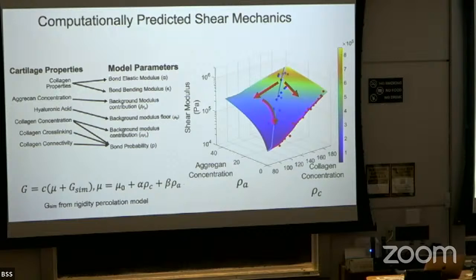So collagen elastic properties in the model will basically inform the stretching and the bending modulus of the stiff fibers, right? Aggrecan concentration is basically the background gel modulus part, this part, right? Hyaluronic acid concentration is the background modulus floor, which is not changing as a function of depth. This part is changing as a function of depth because this rho is going to change as a function of depth. Collagen cross-linking and collagen connectivity, and collagen concentration is going to affect both of these guys,